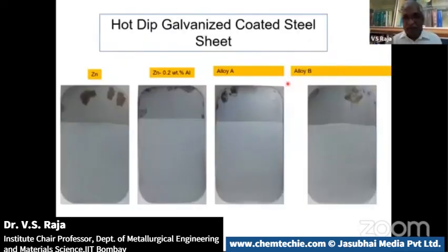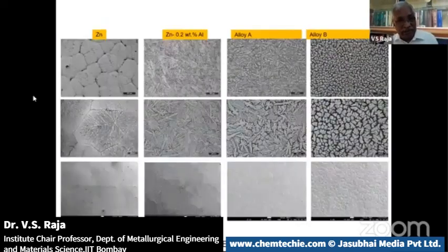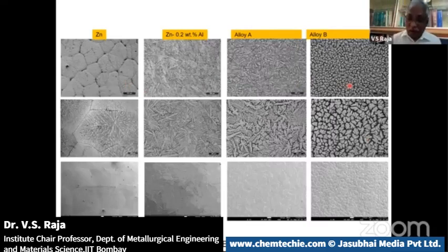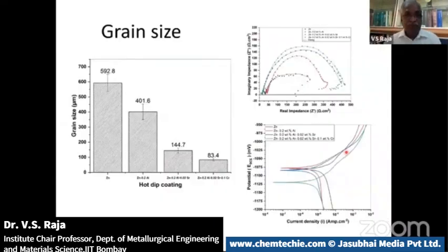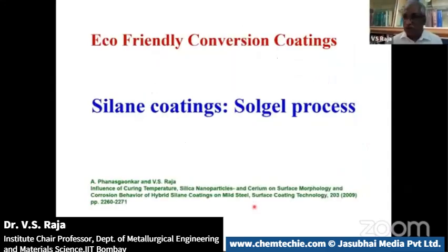How does it happen? This is the kind of visual picture that you see here, but see them in the microscope. You see a significant change in the microstructure in these alloys. This is what we call grain size refinement, and this refinement has given enormous resistance to corrosion. That means, with the same coating thickness, life is increased by 5 times, 6 times. Wonderful thing. You save resources, and it gives you better properties. In fact, these coatings give you a mirror-like finish. The appearance is really wonderful. And again, the grain size, I'm going to skip. I know the time is going to be short, so I'm not going to talk more on that.